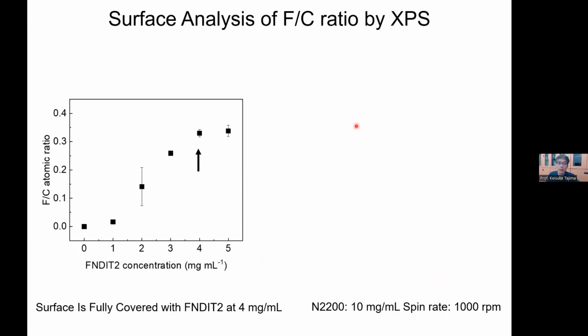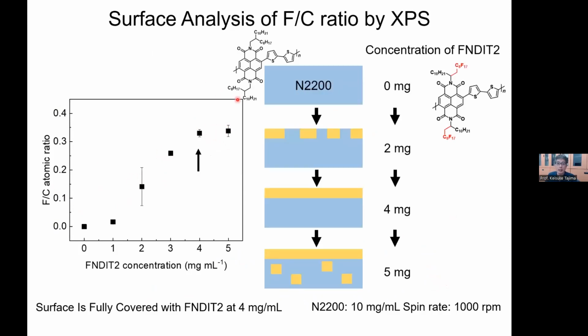So let me show you the analysis. XPS shows that the fluorine accumulated on top of the surface, and it's similar to the previous examples. Firstly, there's no fluorine. Then if you start to add this in the solution, this fluoride chain accumulates on top of the film, and then it gets saturated around here. So its surface is fully covered with this fluoroalkylated NDI polymer.